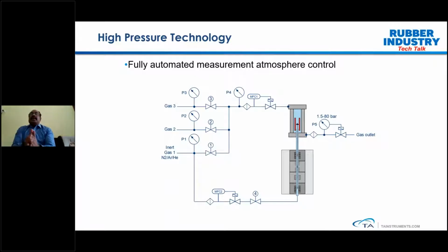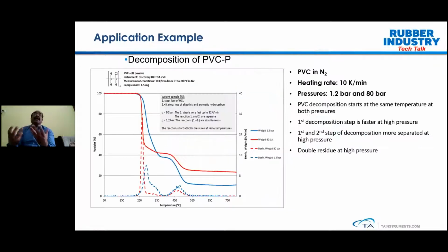The benefit you are getting is that you have a better idea how a particular polymeric material is going to decompose, not only as a function of temperature, but at the same time as a function of pressure. Here I can show you the studies we have done on PVC materials. The blue one was actually performed at a pressure of 1.2 bar. The heating rate is 10 Kelvin per minute. So it's a standard heating rate.